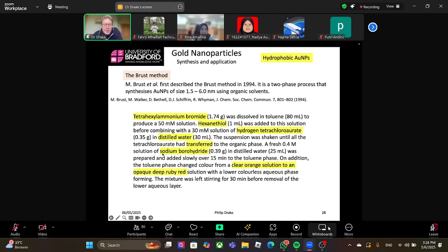You then add in a reducing agent, sodium borohydride. This is what reduces the gold 3 to gold 0. You see a color change. Once you add the sodium borohydride, you can see the color change from an orange solution to a deep ruby red, typical of gold nanoparticles.